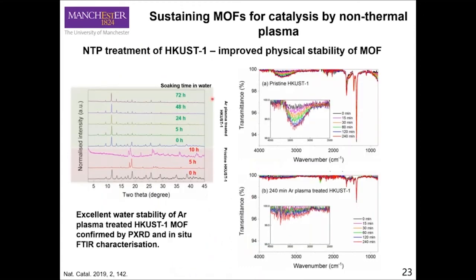And therefore, I think this can be the solution. And we tried it. First, before we tried it, we tried to use non-thermal plasma to treat the HKUST-1. We need to make sure, because non-thermal plasma is a quite high energy field, we don't want to damage this kind of MOF material, which is a hybrid, organic-inorganic combination.